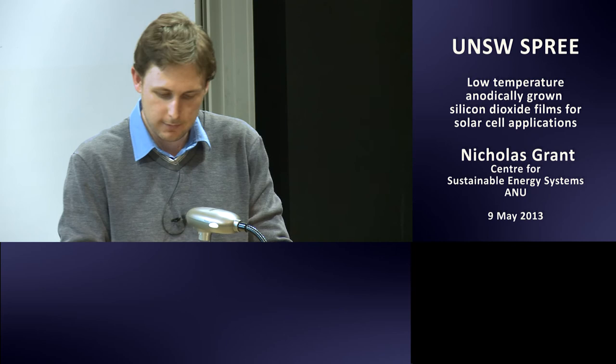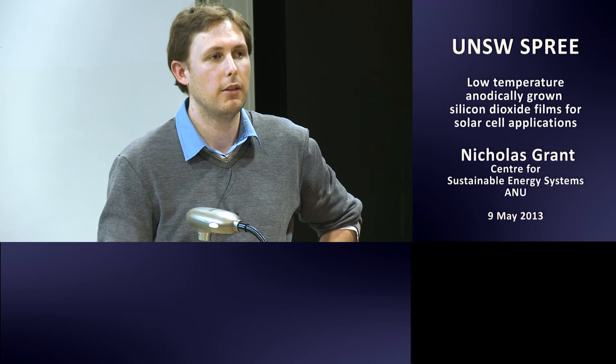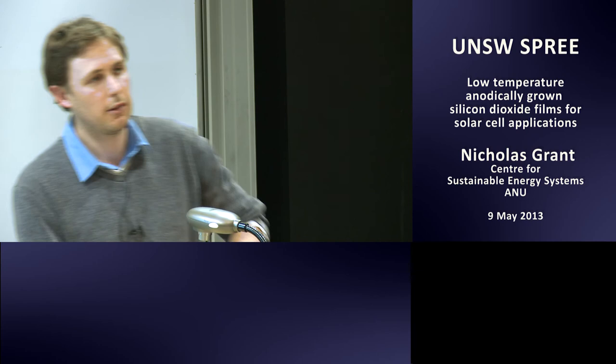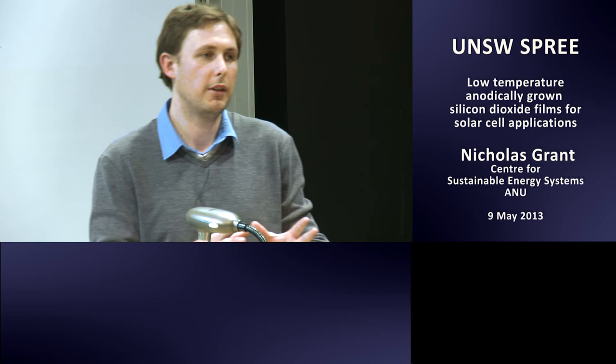Question: How did you measure interface state density? Answer: Using capacitance-voltage with the Terman method. Ideally you'd measure both low-frequency and high-frequency CV curves to extract Dit most accurately, but the films are too leaky for low-frequency measurements. So the Terman method was used with high-frequency measurements only. The absolute Dit values could be slightly off, but the charge values are reliable.